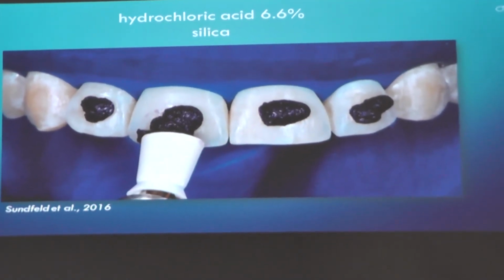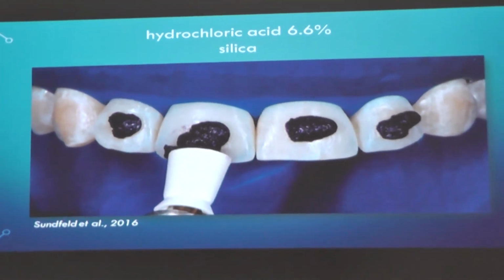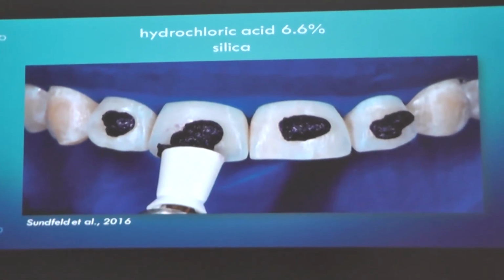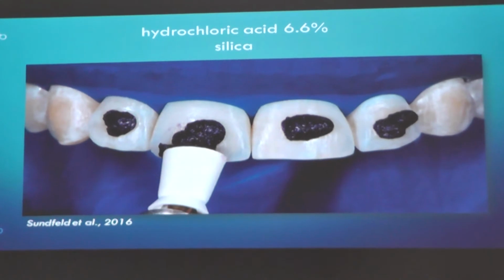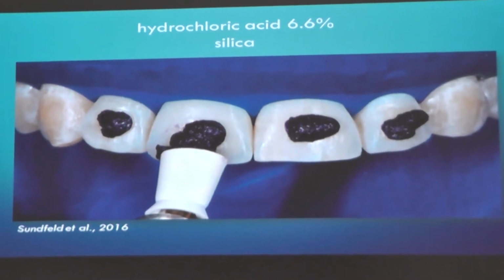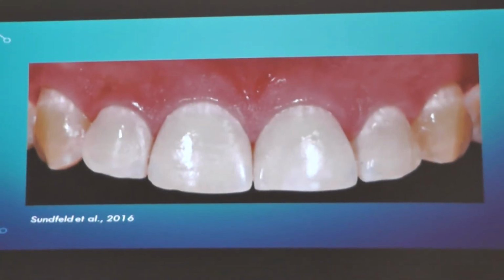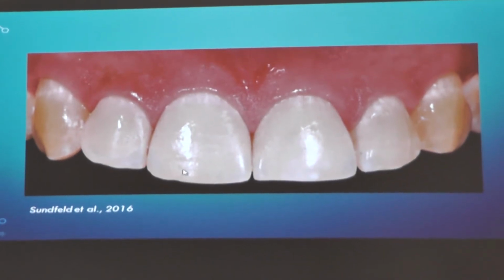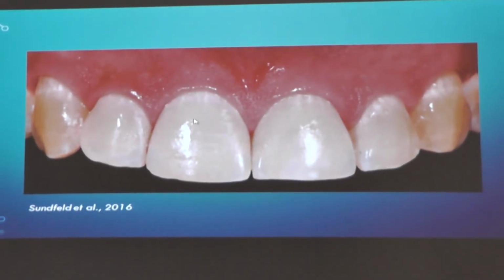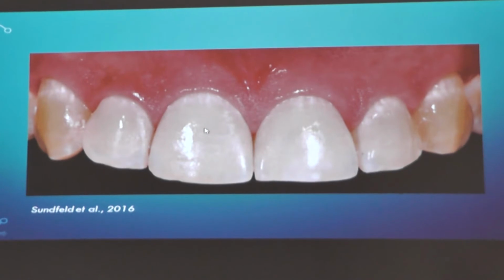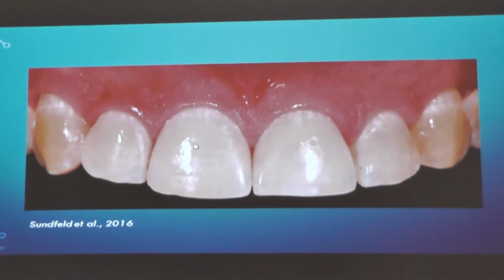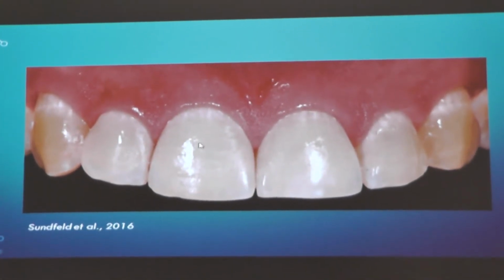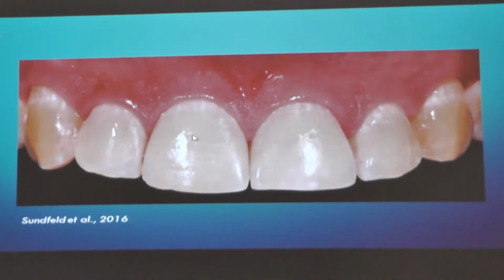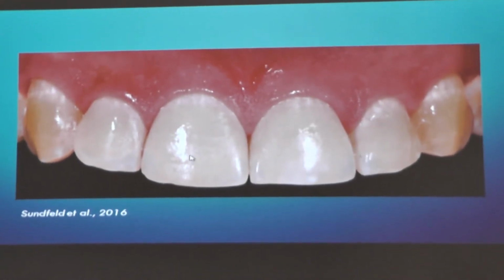And they say it is not clinically significant, so the results are very good. Not a lot of enamel is removed because the thickness of enamel is about 1400 micrometers. And this is the appearance after the procedure, and they said that this very shiny and polished appearance remained during the years.